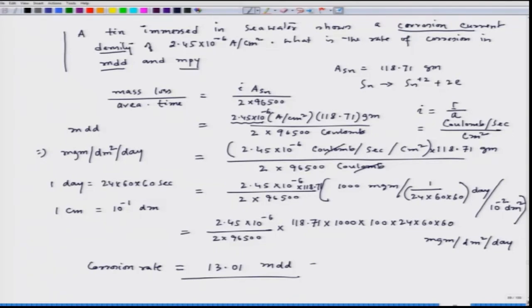Now, we have to find out the corrosion rate in the form of MPY. There are two ways. Once you know MDD, you can convert that MDD into milli inch per year, or you can start with the basic equation, which is corrosion rate is equal to I A M divided by N F rho. Here M is nothing but the atomic weight of tin, and rho is the density, and then we can write it as 2.45 into 10 to the power minus 6. It is basically ampere per centimeter square.